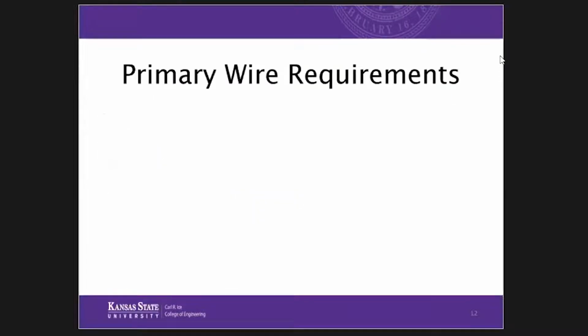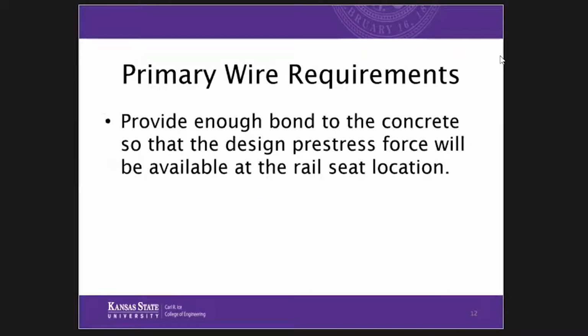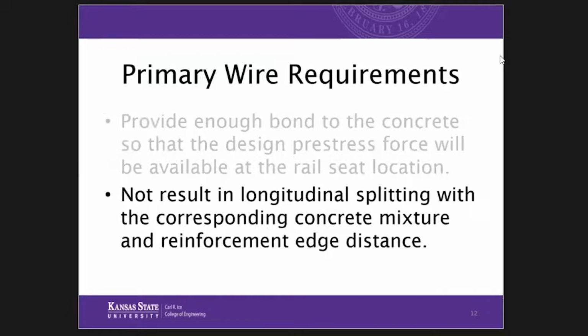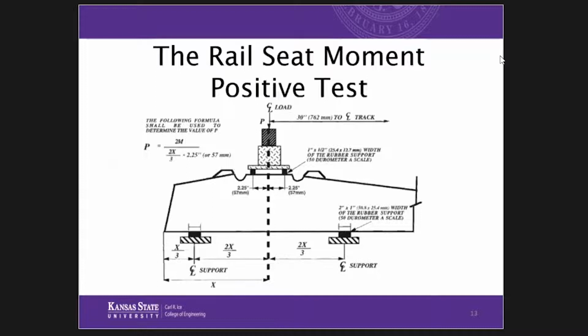So the primary wire requirements are to provide enough bond to the concrete so that the design pre-stress force will be available at the rail seat location, and then not result in longitudinal splitting with the corresponding concrete mixture and the reinforcement edge distance. So we wanted to provide bond, but not produce splitting. The way we typically verify bond at the plant is we do a rail seat positive test. We actually apply a load at a distance from the end until we get a crack.